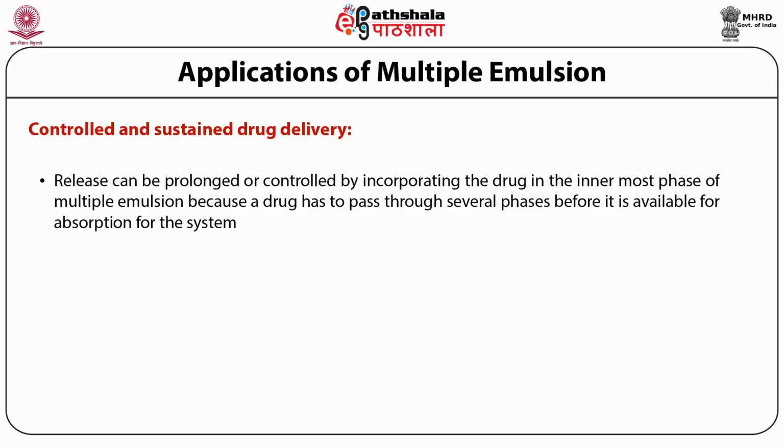Prolonged release multiple emulsions of 6-mercaptopurine were prepared by Khopade et al. by the incorporation of sphingomyelin and monosialoganglioside GM1 in the oily phase and by coating with lipid grafted polyethylene glycol. It was concluded that PEG-PC coated multiple emulsions are superior as prolonged release and extended blood circulating carriers compared to the multiple emulsion having the GM1 or SM.